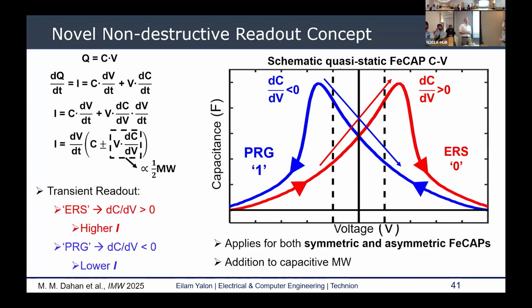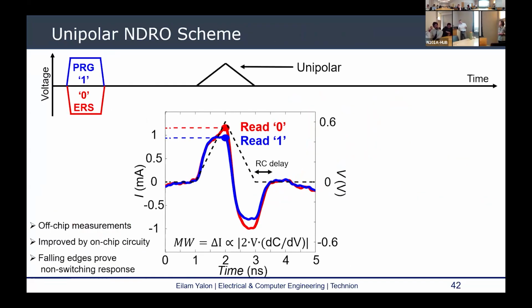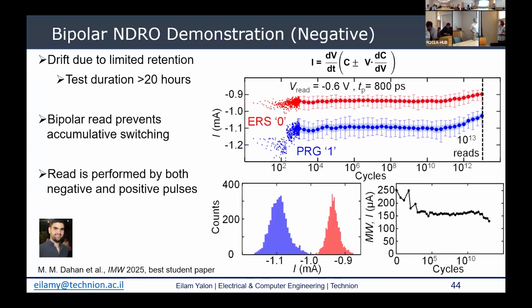Leakage current doesn't, it is a very fast measurement. Leakage current doesn't play any role because it's so much below. These are really huge currents, so it doesn't play a role in this view. Because the displacement current goes as 1 over delta T, and if you look at the current, this is milliampere current, because the delta T is so small, the leakage current is so much lower. So that's not an issue for this type of measurement.